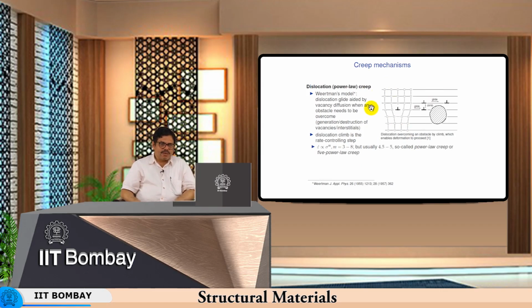Now, when we come to power law creep, there are different models. So, we have Weertman's model, where we say that the dislocation glide is aided by vacancy diffusion. Dislocation glide is facilitated by vacancy diffusion, because when an obstacle needs to be overcome, let us say this obstacle is present, normally this dislocation would get held up at this obstacle, and it will not be able to pass through unless it is able to circumvent that obstacle or cut through that obstacle. But now, because of the possibility of diffusion, these one or two atoms at the top can diffuse out, and then it can lead to dislocation climb, and once it has climbed by, let us say, one lattice parameter, then it can glide avoiding this obstacle.